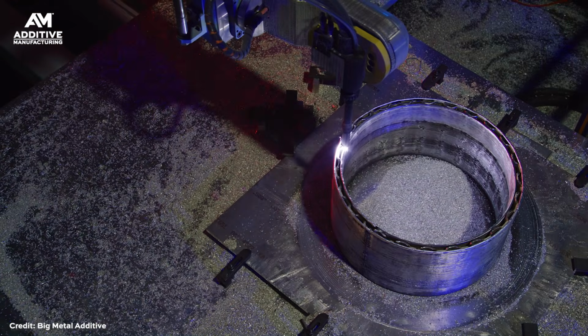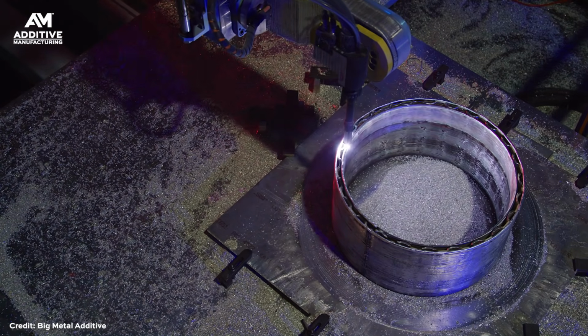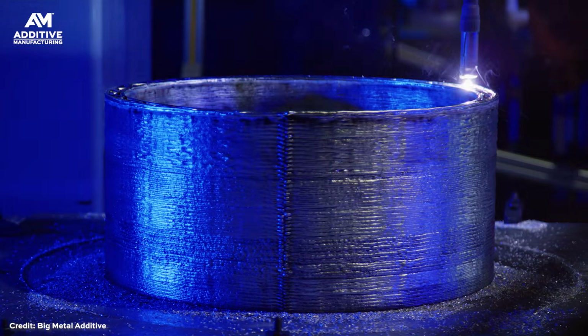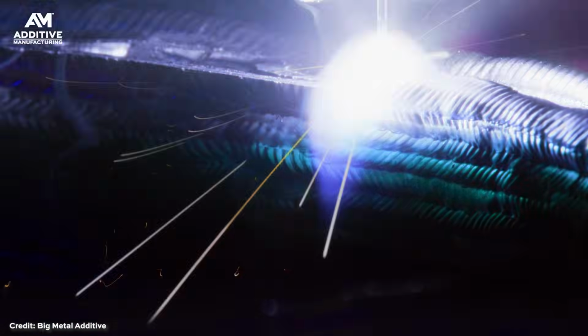Before we did the test, I made some guesses about what it would take to rip the thing apart or to crush it. I think I drastically underestimated the amount of load that it would take to damage the tank. Long ago, when I first started in additive manufacturing, people said, oh, you're putting it together a layer at a time. It's just going to tear apart at the layer interfaces. Well, guess what? It really doesn't. This is good metal. This is good casting equivalent, forging equivalent, foundry equivalent metal that we're making. And so all the test results that we're getting from this just give us more and more confidence that the metal is good and that we can make structural parts with it.